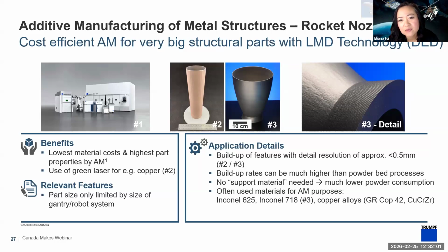A good example of this, which was developed by TRUMPF, was using a green laser wavelength for highly reflective materials like copper alloys. We've done this on GRCop-42, a NASA-developed copper alloy, and also copper chrome zirconium, which is also very commonly used. With these, the build-up rates can be much higher because you're not losing a lot of laser energy from the reflectance of the material. So more of the laser light is being absorbed into the material, which makes the process more effective.